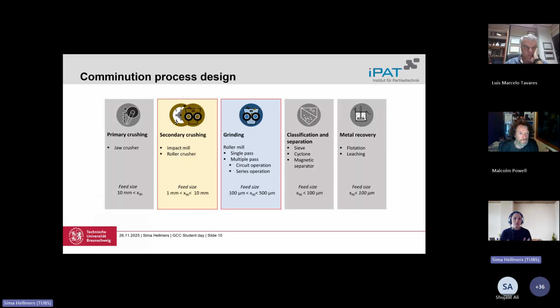We have a target size and we want to reach it using different mills. We can start like with usual ores, that is, we can start with a jaw crusher and keep on reducing the size using secondary crushers like impact mills and roller crushers, and then take the finer particles that are below 500 micrometer to another roller mill and grind them so we can reach our particle size. Of course, most of these processes were just done once as a single pass and not in a circular way.